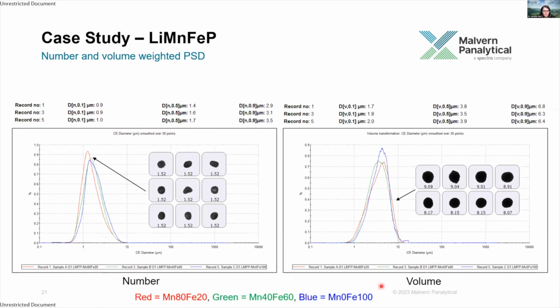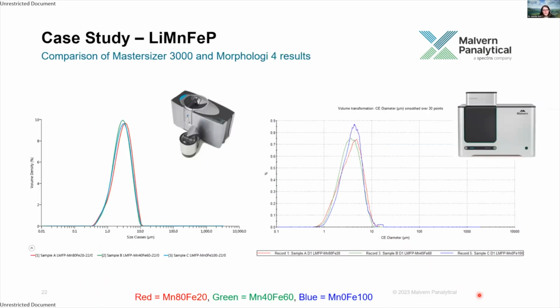We are also able to transform to a volume-based distribution, like what we've shown on the right, which shows that by volume, these materials are very similar. We can then compare the volume-weighted distribution, which we measured on the Morphologi 4, shown again here on the right, to that measured on the Mastersizer 3000, so using laser diffraction. And what we can see here is that we have very good comparability between the two techniques.